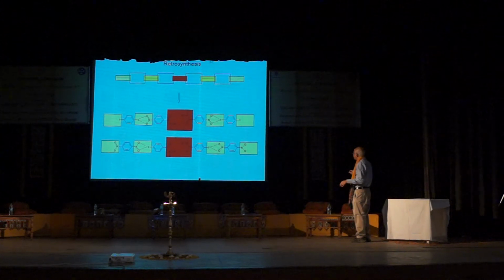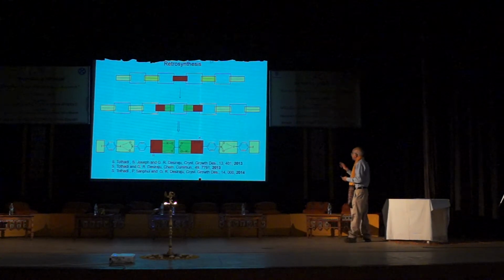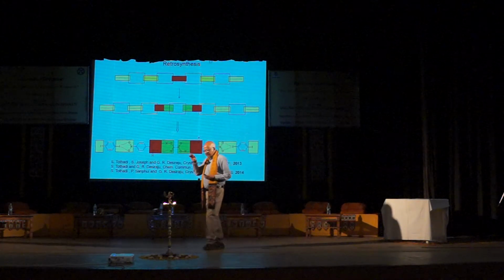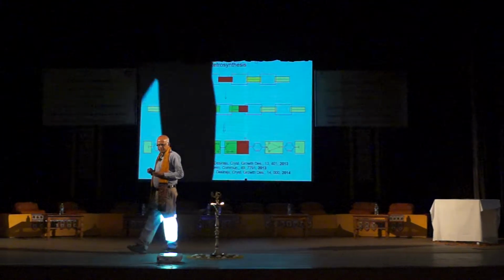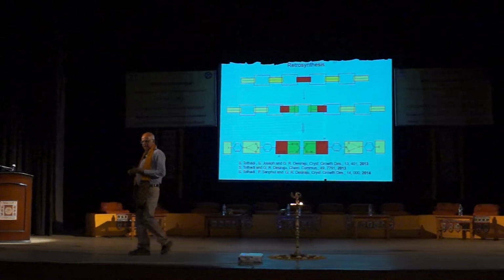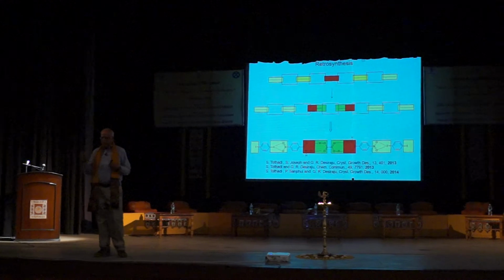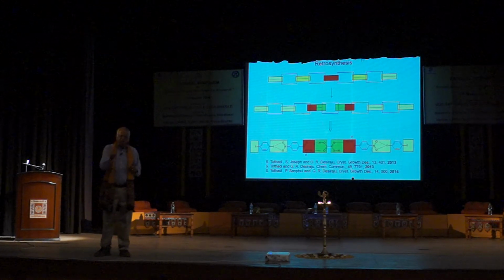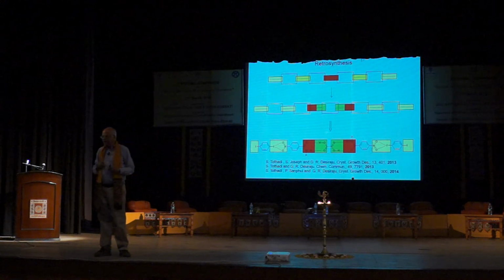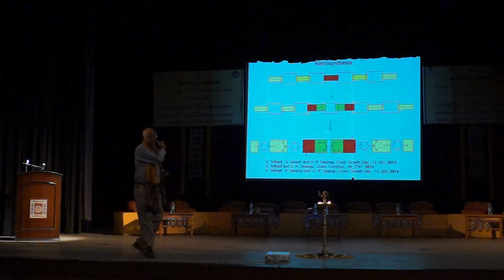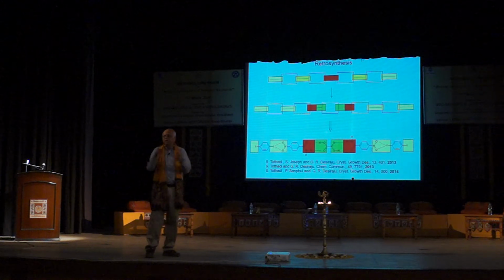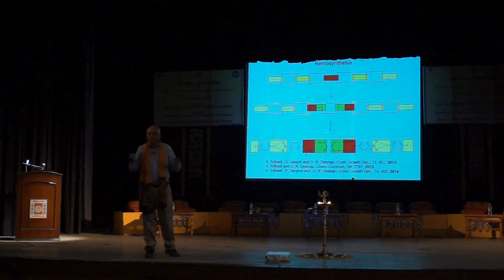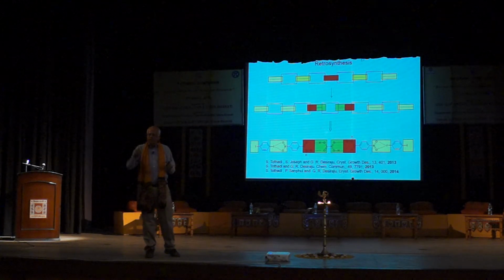Now you know what I'm going to do next. I take the amide which does this and then I put the dicarboxylic acid. So for the first time we are getting a 3-component crystal. Now what have I done? I have used the supramolecular homologation with acid, and I have used the insulation of the nitro group on the other side. Each thing does its own stuff. They don't start talking to each other. You don't want these functional groups to start talking with each other too much, because then your whole synthetic strategy will go wrong.